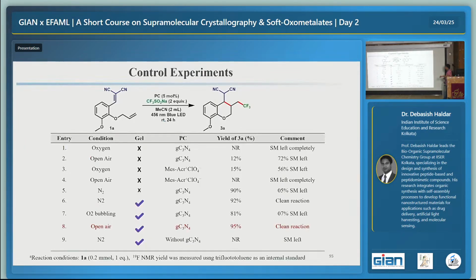Then we have done this reaction with the help of my colleague Suresh Devarajulu. So the photocatalyst g-C3N4, CF3SO2Na, 2 equivalents, in acetonitrile, with 456 nanometer blue LED, room temperature, 24 hours. So the reaction is happening. This is cyclization followed by this CF3 installation on this part.